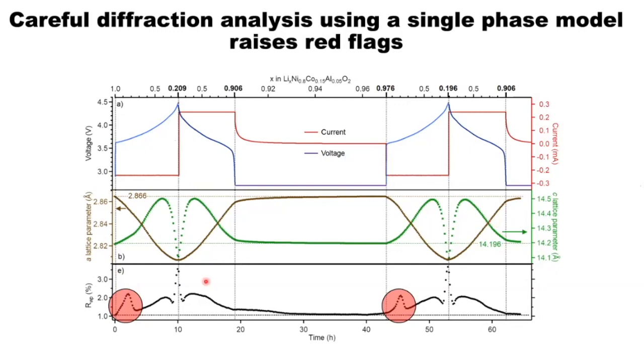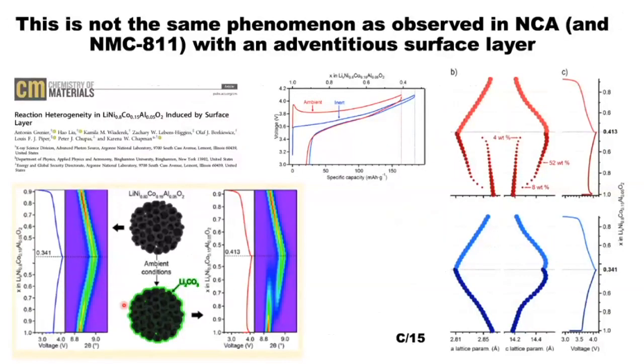So careful work by Antonin looking at the diffraction pattern using a single phase model to fit the patterns on charge and then discharge raised red flags, particularly when looking at the R factors or the profile fits at the beginning of charge for single phase. And so what he found was that he really needed to model this with two phases.